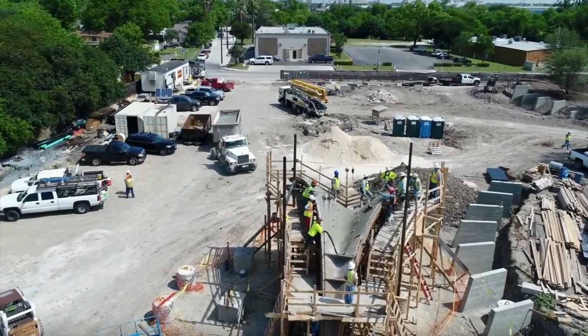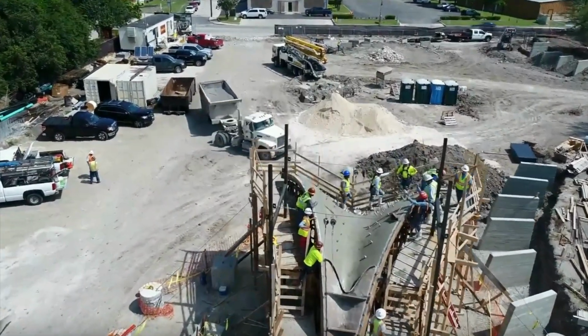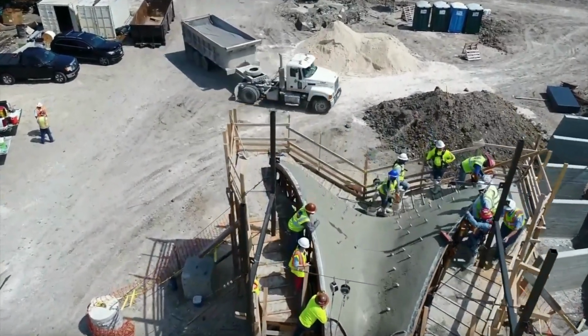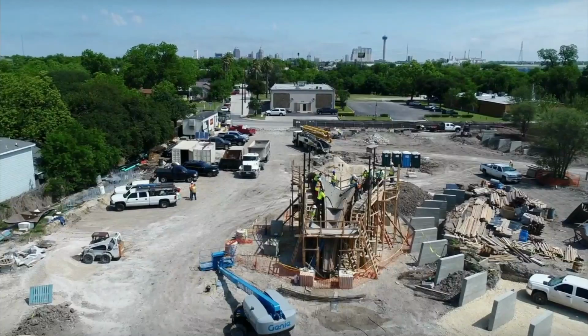So you can see here this laborer. It took a while to train them to broom the surface in the correct direction because it's not totally intuitive when the whole petal is tilted at a 45-degree angle, which is the downhill direction. And they had to then build these brooms that had 12-foot long handles, and it's quite amazing to see.